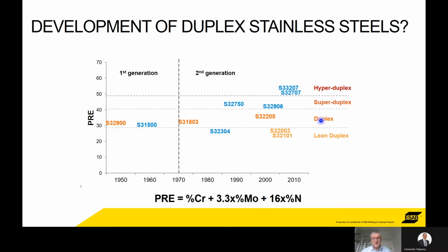Duplexes, this standard duplex is a fairly common grade these days. The standard duplex has got a pitting resistance equivalent number of greater than 32. The super duplex needs a pitting resistance of 42. And then we've got this thing called hyperduplex. Now, hyperduplex has a PRE above 48. And the difference between these, the higher that you go up the scale, the more resistant these things are to pitting corrosion. And similarly, the stronger the material gets.